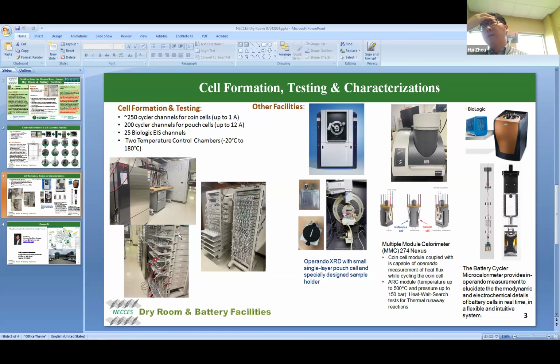Besides that one, we have around 25 BioLogic EIS channels if you need impedance measurement. And we have 2 temperature control chambers. This can control the temperature from -20 to 180 degrees Celsius. It's especially for projects where you need temperature control for the test. And also for the high capacity pouch cell, we need this kind of oven for safety consideration.